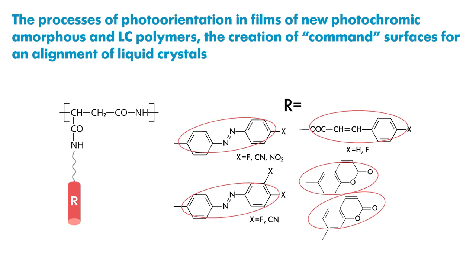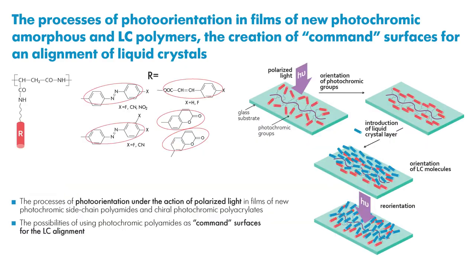Using this photoregulation principle, we have created new so-called command surfaces for the orientation of liquid crystals. For this purpose, a series of new photochromic polyamides with various side photosensitive groups based on azobenzene, cinnamic acid, and coumarin were synthesized. As I noted above, the irradiation of such films leads to the orientation of photochromes perpendicular to the plane of light polarization.